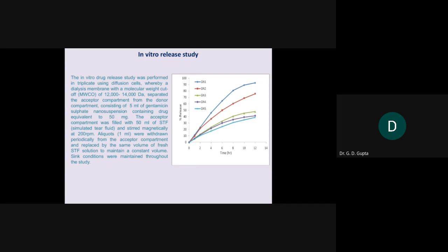up to 12 hours. The pattern of release of the drug was nearly uniform. You can see from this graph that the release was controlled, and it is released slowly and slowly, and up to 12 hours more than 90% of the drug gets released.